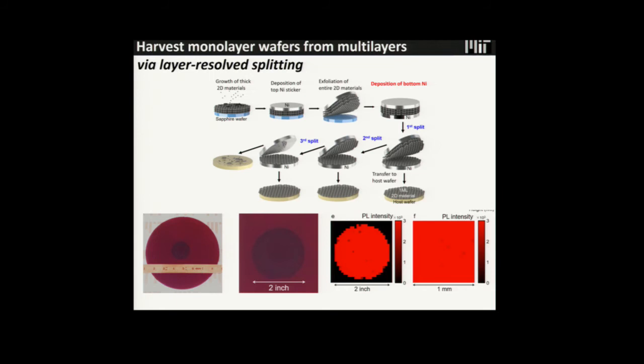Then we transfer it onto the 2-inch wafer. This is a magnified image, and we are quite happy to see this PL mapping. We did a PL mapping of this monolayer tungsten sulfide, completely separated from the very thick tungsten sulfide on sapphire. As you can see, it shows the direct band gap, very strong PL.